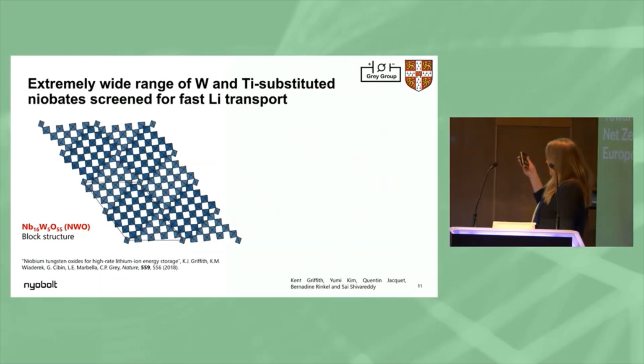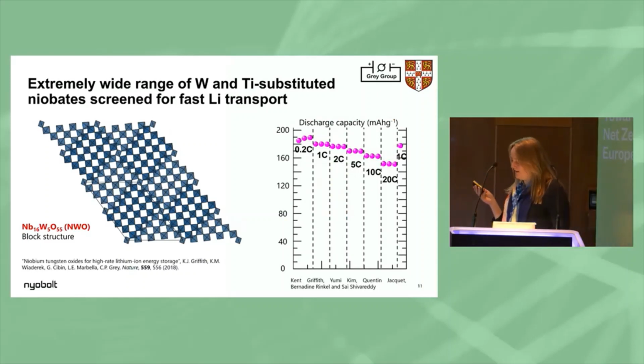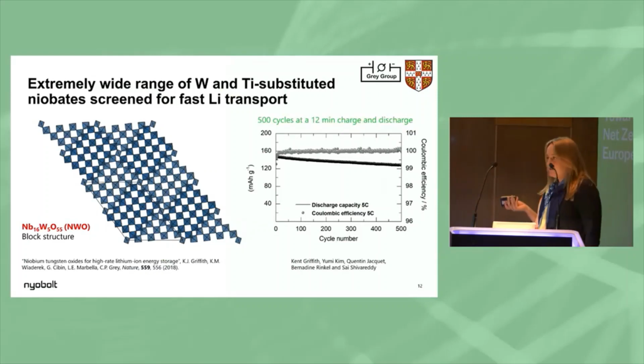So Claire obviously showed this slide earlier, but Kent in Claire's research group and others screened a large number of tungsten and titanium substituted niobates, looking at the structures, looking at fast lithium ion transport. And one of the structures that was developed was the niobium tungsten oxide Nb16W5O55 structure. And this really did demonstrate that high rate capability, so fast charging. So a 3-minute charge demonstrated in this material. Looking at how that maintained over cycles, in the research work, we saw 500 cycles with a 12-minute charge and discharge, and this is all reported in the Nature paper published in 2018.